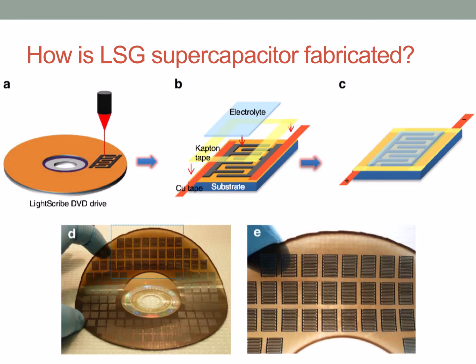In image B, copper tape is applied along the edges to improve the electrical contacts, and the interdigitated area is defined by polyimide, otherwise known as Kapton tape. In image C, an electrolyte overcoat is then added to create a planar micro-supercapacitor. In images D and E, the final images show planar capacitors with remarkably clear and high-resolution interdigitated fingers with 150 micron resolution.